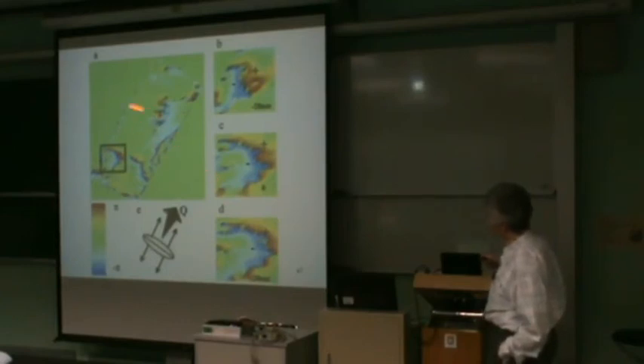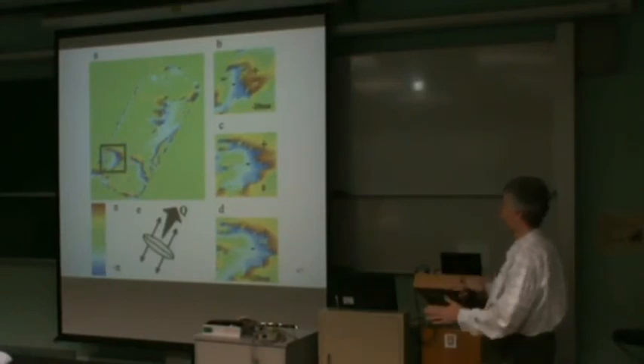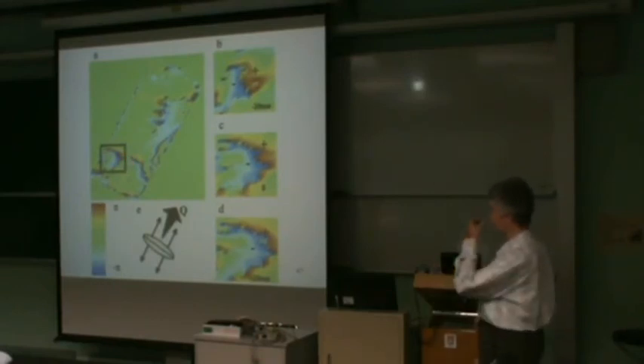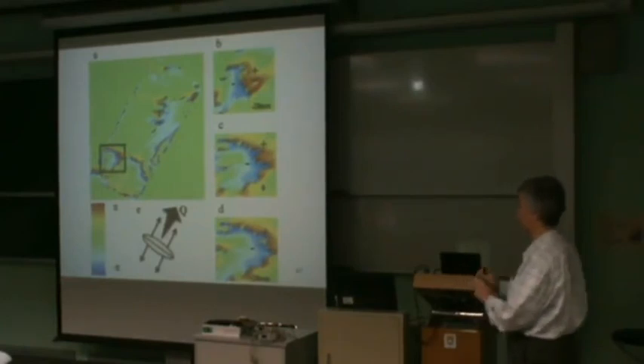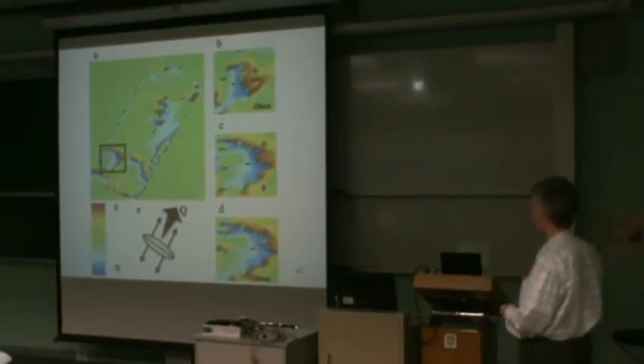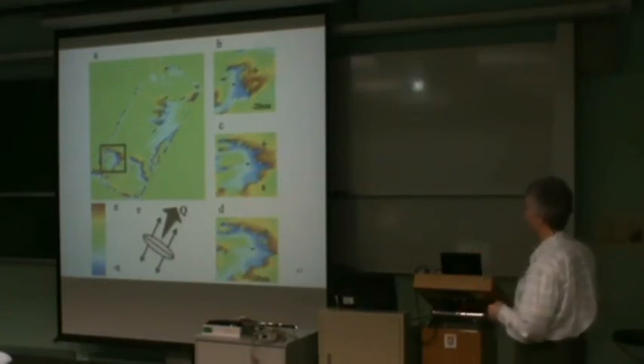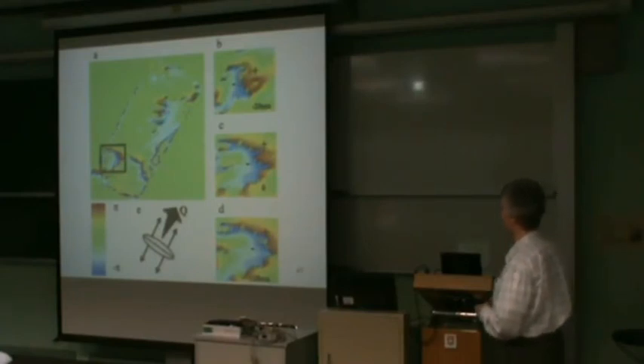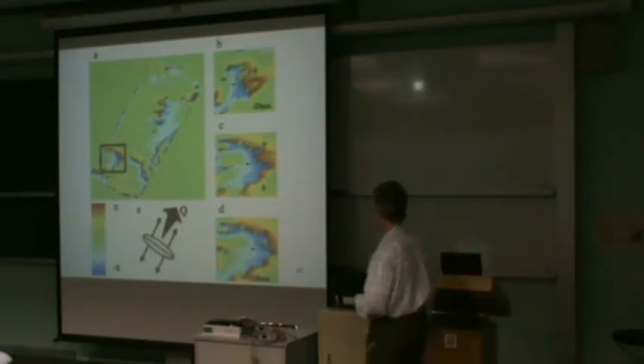What we're seeing is relatively few dislocations in the middle of the sample, but they're occurring at the edges where the gradient of the intensity profile is highest. So that's the place where I think you would expect the fracture to take place, but we haven't confirmed that. So we're seeing roughly at the half height point of the beam is where we get the biggest number of these dislocation loops occurring.